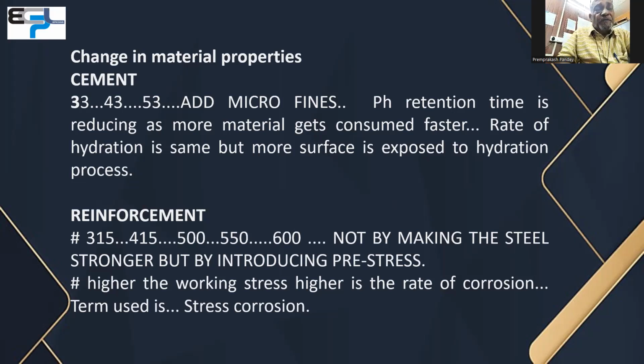Reinforcement is the same issue. We used to have 315, then 415, 500, 550, 550D, then probably 600, and next will be 650. This property or performance of steel is being achieved partly by chemical manipulation and partly by changing the crystalline structure of the steel by introducing pre-stress in the steel. And one fact is well known in the mechanical industry: the higher the working stress, the higher the rate of corrosion. The term used in this study is stress corrosion. Any material at a higher state of stress is prone to it. This is because of change in material property.